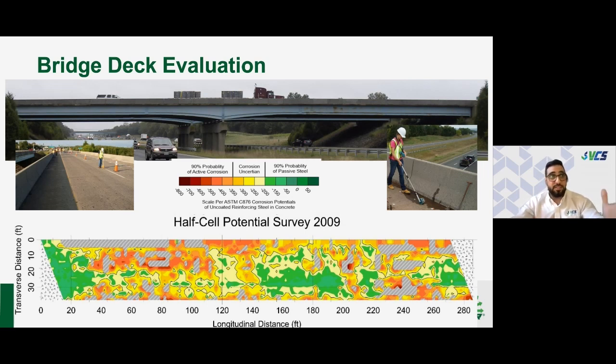I just inspected a parking garage where they had installed a conductive coating on the underside of several of their floors and installed the rectifier, and they were seeing the coating just disintegrating. So they called us, I went out there, took a look at it, and when I went to open up the rectifier, none of the wires were connected to the rectifier terminals. Obviously there was a disconnect between maybe the contractor conducting the work, maybe the engineer in charge of the cathodic protection, but the system was never commissioned. And that's going to leave a bad taste in the owner's mouth, and they're never going to want to go back to that. But,